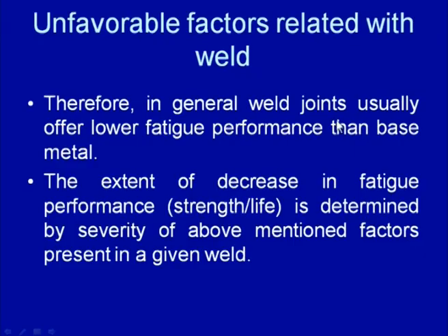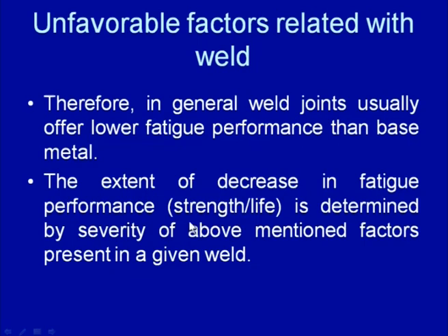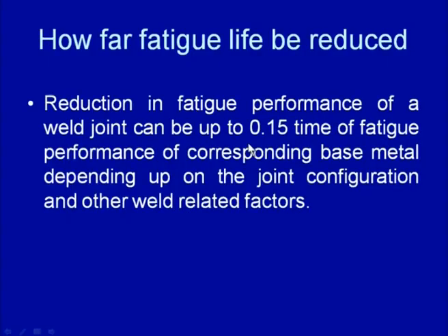So, because of these unfavorable factors related to the weld joint, in general weld joints usually offer lower fatigue performance than the base metal. And the extent of the decrease in fatigue performance is determined by the severity of the above factors present in a given weld. So, how far will the fatigue life of the component be reduced due to welding? That can be up to 0.15 times the fatigue performance of the corresponding base metal, depending upon the joint configuration and other weld related factors.